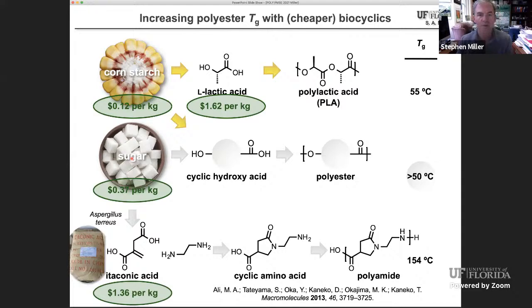So we got some inspiration from my friend Tatsuo Kaneko in Japan, and he had worked on taking this very inexpensive itaconic acid molecule, which is a sugar fermentation product available at a little over $1 per kilogram, so that's well under $1 per pound. He attached ethylene diamine to it, which of course made this amino acid, which then he could polymerize to make polyamide, which has a very attractive glass transition temperature, 154, maybe some degradation properties.